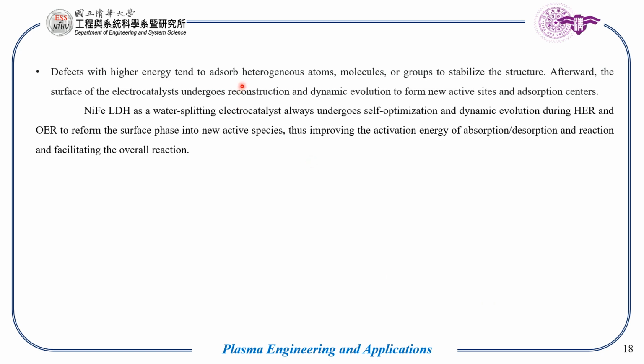The defects with higher energy tend to absorb heterogeneous atoms, molecules and groups to stabilize the structure. Afterward, the surface of the electrocatalyst undergoes reconstruction and dynamic evolution of new sites and activation centers. This point talks about how these defects also form after plasma treatment on any material. These defects have higher energy and tend to react with the surrounding material to adjust themselves, and the reaction also increases in those defective areas, and thereby they also increase the efficiency of many reactions such as hydrogen evolution, or it can also be applied for oxygen.